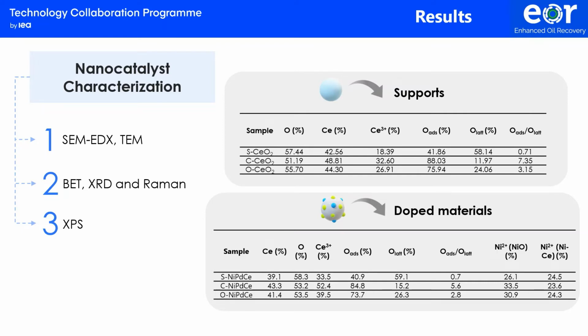Also, the content of ceria 3+ ions increases in the same order, and the presence of these ions is a consequence of oxygen vacancy formation. It promotes the activation and promotion of oxygen in the bulk and on the surface of the nanoparticles.